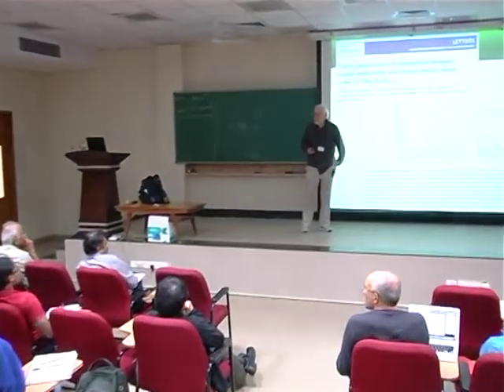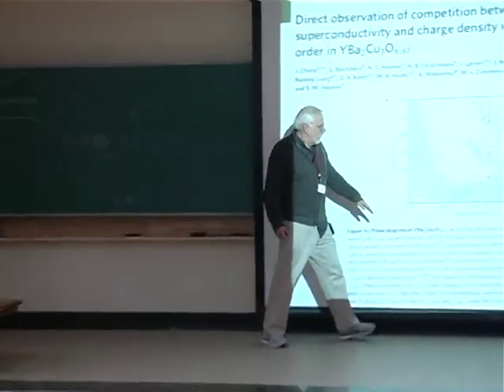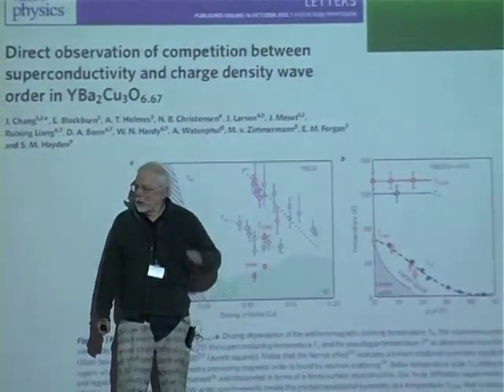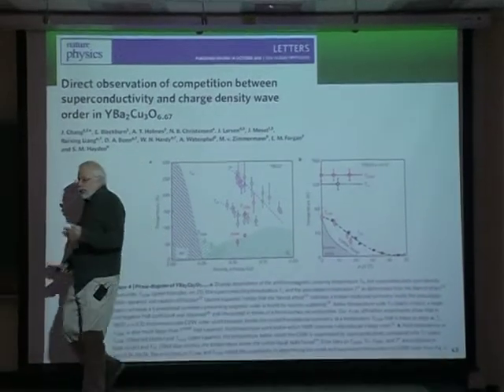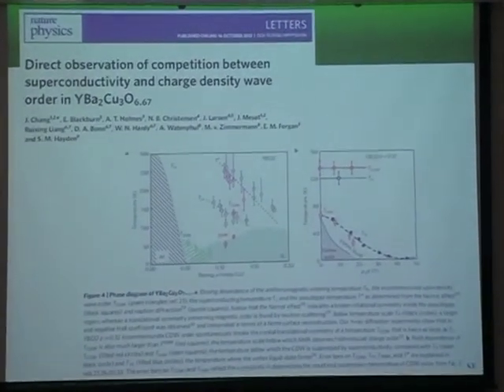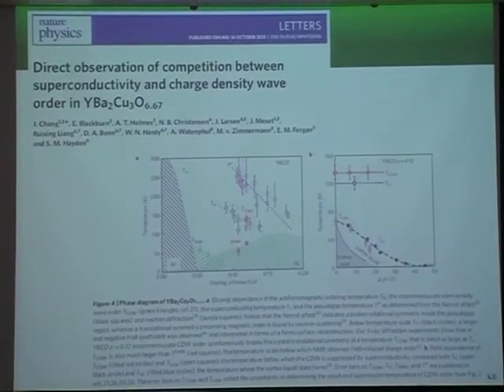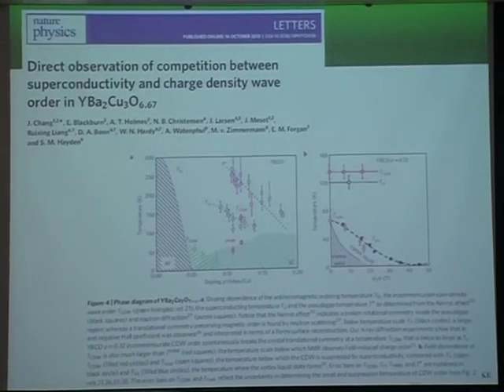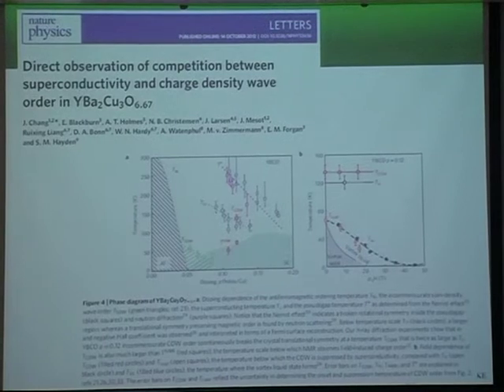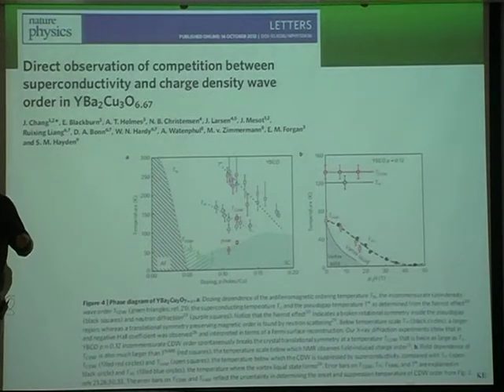So in LSCO, in lanthanum copper oxide, these are really stripes. In other words, you have a charge and spin at the same time. Here it is different. It is really charge only, no spin modulation. Now, why did it take such a long time to see? Well, there are two reasons. One is that there's been a great improvement in resonant inelastic X-ray scattering and X-ray measurements in general. And the other reason is that phase space is huge.